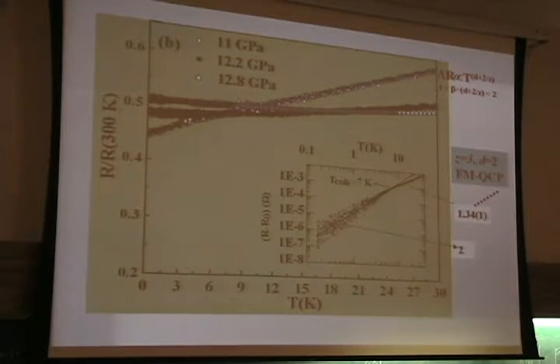this power law is given by this formula, where beta is (d+2)/zeta, and d is the dimensionality of the system, okay? So we found this exponent for this power law behavior that is related to a ferromagnetic quantum critical point with zeta equal 3 and d equal 2, because it's very close to the 4/3 value of beta. Okay.